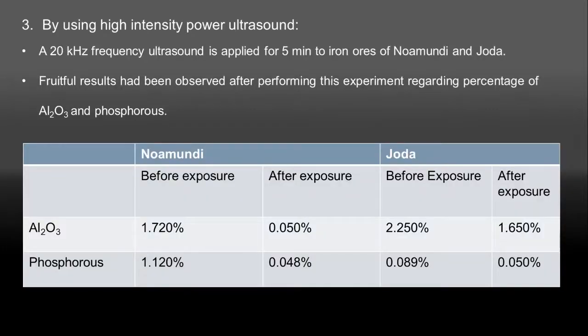In this slide, we will see an experiment in which samples of iron ore from Noamundi and Joda have been exposed to high intensity power ultrasound of 20 kHz for 5 minutes. After the experiment, good results have been obtained in terms of decreasing the content of alumina and phosphorus. As you can see the figures of Noamundi iron ore, before and after exposure, the alumina content has decreased from 1.7% to 0.05%, and the same happened in Joda iron ore also. Phosphorus content is also decreased, as you can see.